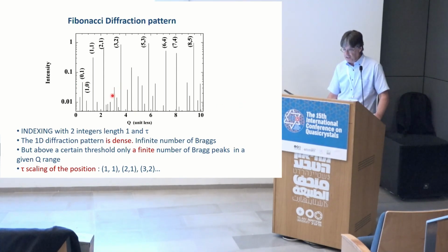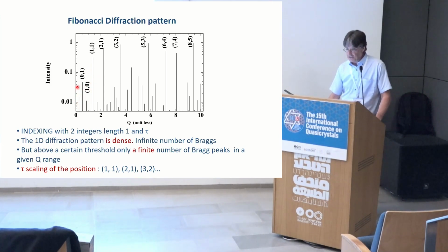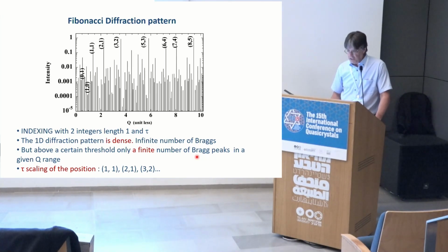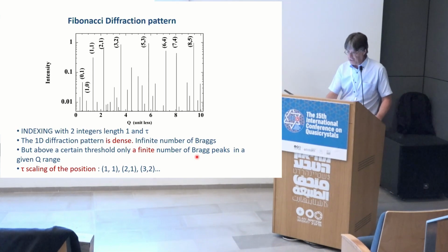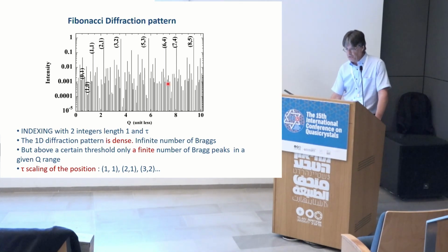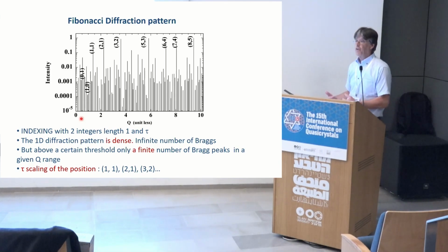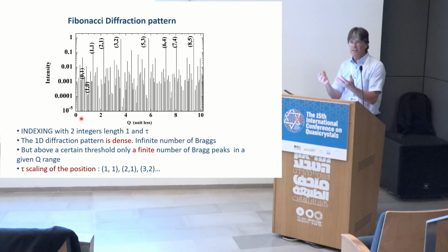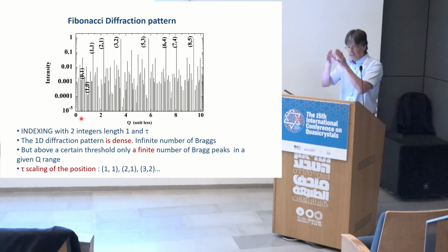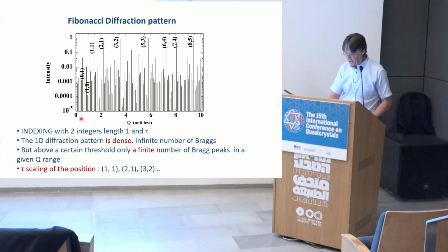You have sharp bright peaks that can only be indexed with two indices, and the two length scales here, here, and here, 0,1 and 1,0, are related by the golden mean tau. They are irrational, and again, we have these two irrational length scales that make up the diffraction pattern. Because it's infinite and very well ordered, we have, in theory, an infinite number of Bragg peaks. If I change the scale here from 10 to the minus 2 to 10 to the minus 5, you see that you have more and more Bragg peaks showing up. If you went further, you would have more and more peaks. In reality, we'll see that we have some cutoff, and hopefully we have a finite number in a finite range of reciprocal space.